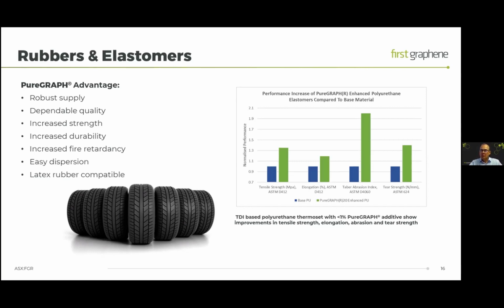On the right is a typical performance graph that we see for performance enhancement in rubbers. This particular example is in polyurethane systems that are used for mining wear liners. I'll talk more specifically about this example in a little while. But simply looking at the chart, this is normalized performance, with the blue bars being polyurethane without PureGraph and the green bars being polyurethane with PureGraph.